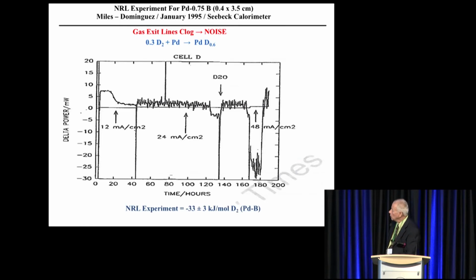Now, in January 1995, I went back to NRL trying to help them get excess power because that was the thing blocking the Navy program. They had never found any sign of excess heat, and there's another reason for that, and I could go into it, but they changed my calorimetry so the error was plus or minus 250 milliwatts. Well, that makes a big difference, because most of my effects would be in the error range. But they've just gotten a new Seebeck calorimetry, which is very good, apparently.